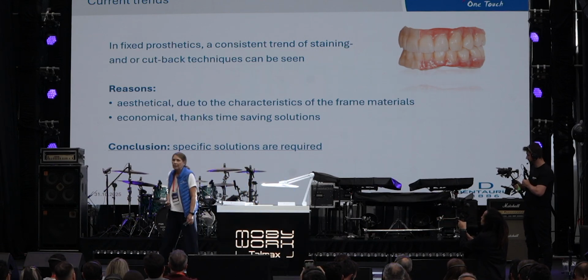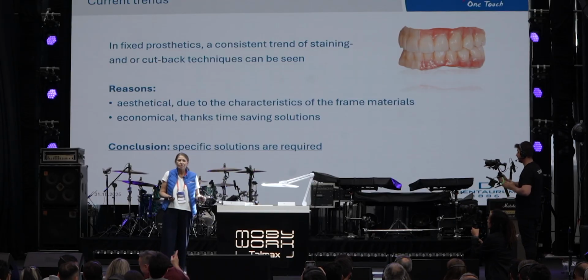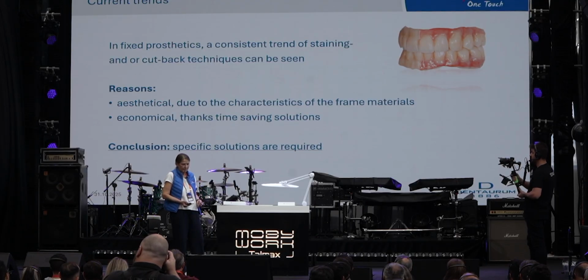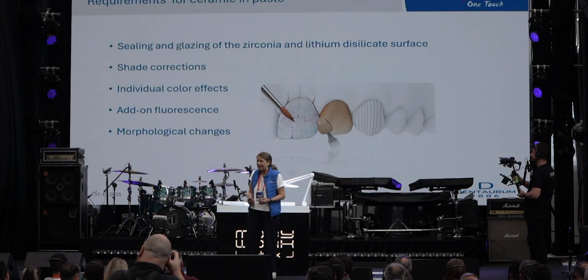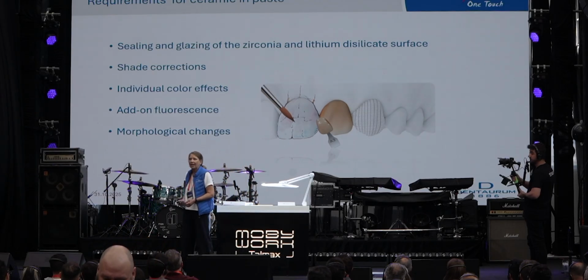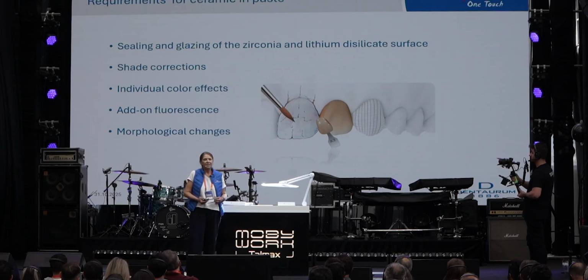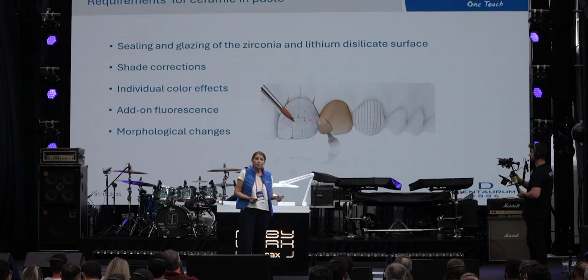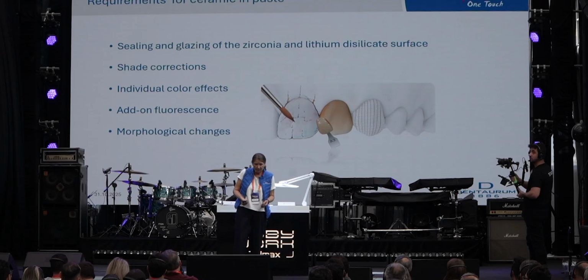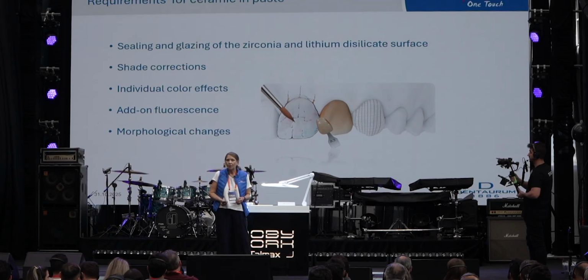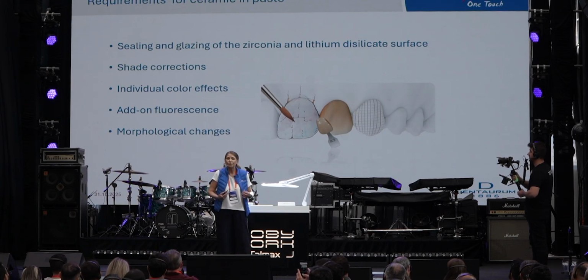More than 10 years ago, we noticed that the trend was going more and more to the staining technique, because the lithium disilicates and also the zirconia material were getting better and better concerning translucency and also shading. So we decided to develop a material that's much more than staining. We wanted a material which is sealing and glazing, which does shade corrections, where you can also create effects. We wanted the material to put on fluorescence, because zirconia is normally not fluorescent at all. And that's also very important. We wanted a material where you could also make morphological changes, improvements.